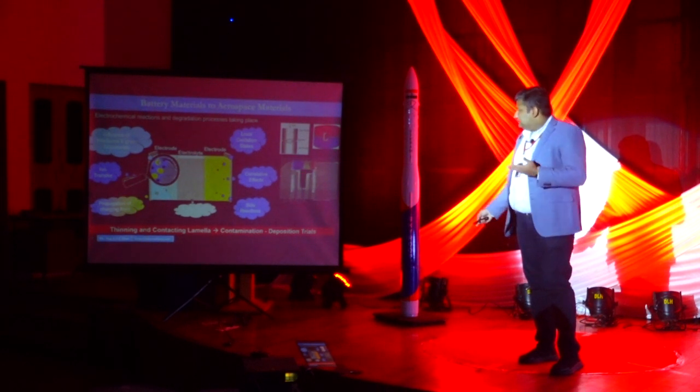And then we also had exposures to heavy doses of electrons because of the fact that we were looking through an electron microscope, how this could result during the process of preparation, during the process of imaging at various stages. And then there was also a lot of thinning which was happening by using gallium ion beam and contacting of the lamella inside the scanning electron microscope, what you can see here, the lamella. All these things had lot of effects which were resulting in the experiments.